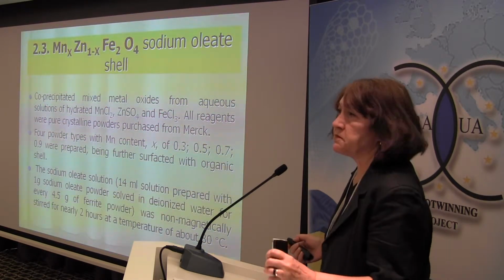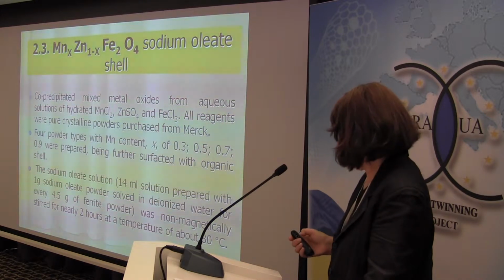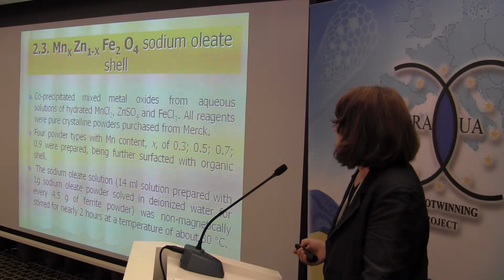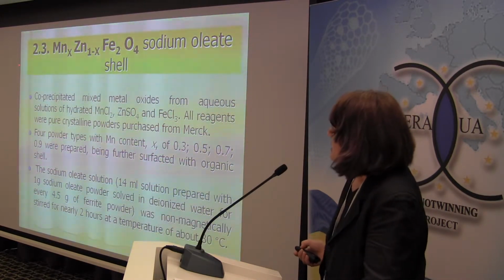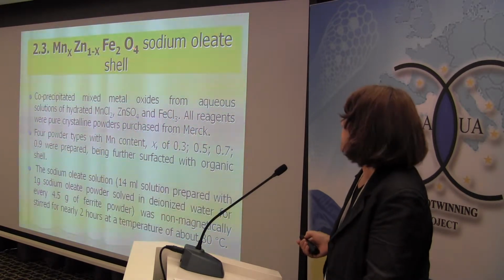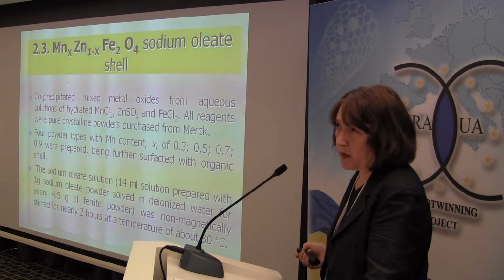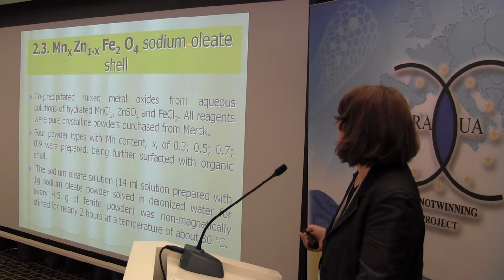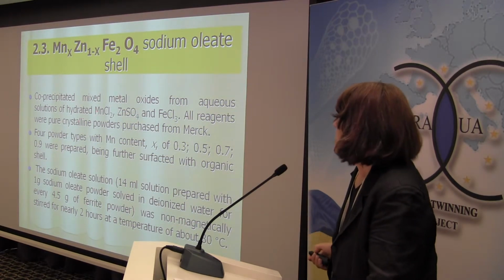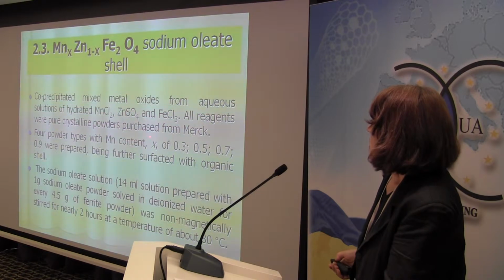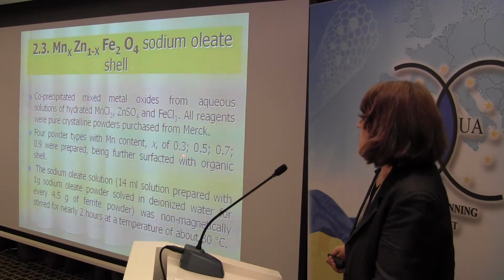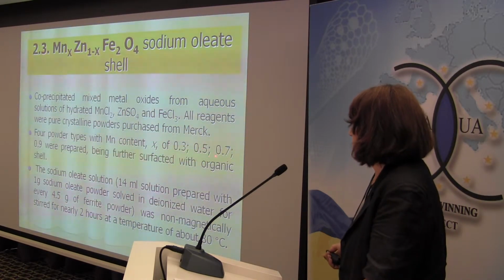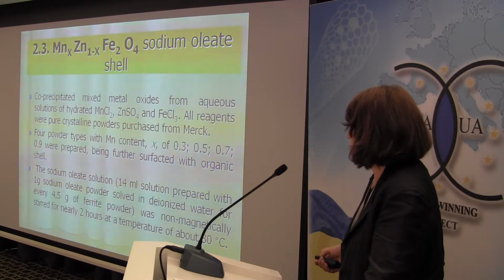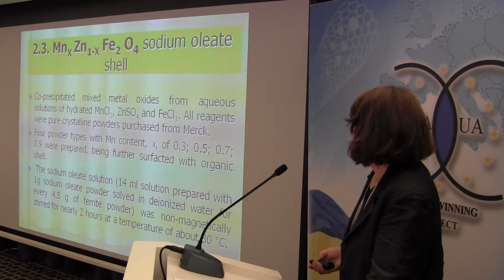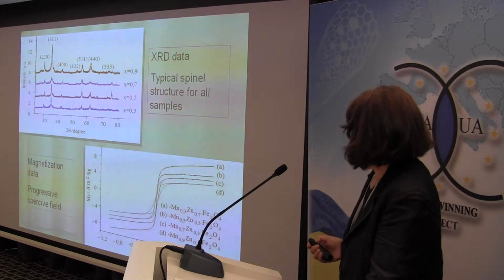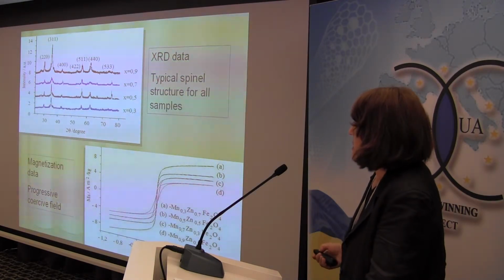In the final part of my presentation, some words about the manganese, zinc, and iron nanoparticles coated also with the oleate from a sodium oleate molecule. A series of products with increased manganese content from 0.3 to 0.9 were prepared and characterized. Here are the crystallinity data.